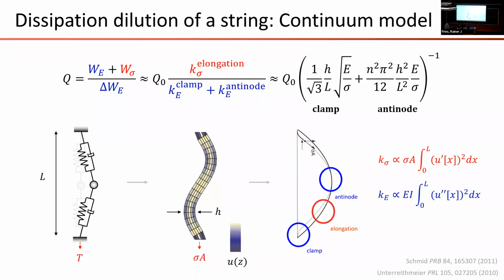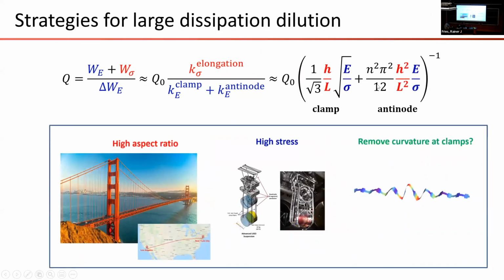So at the end of the day, you can derive a formula which works pretty well for string and membrane-like mechanical resonators. It says that the quality factor due to this tensile stress gets amplified. And there's two factors here due to the ratio of the stress-induced stiffness to stiffness of the clamp and stiffness of the antinode. The important takeaway is that this dissipation dilution factor depends a great deal on the tensile stress, on the aspect ratio of the device, and it depends also on the ratio of the applied stress to the intrinsic elastic modulus.